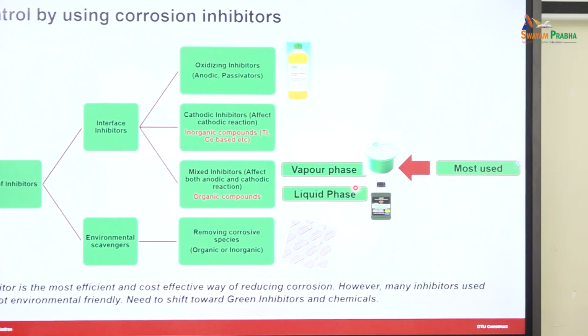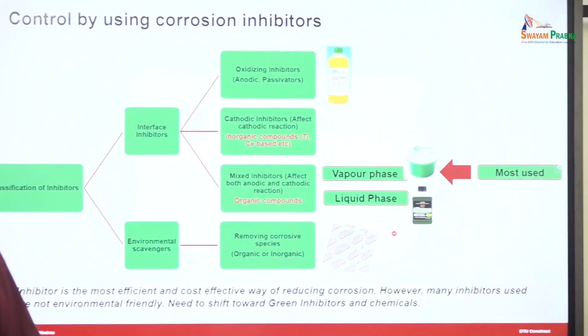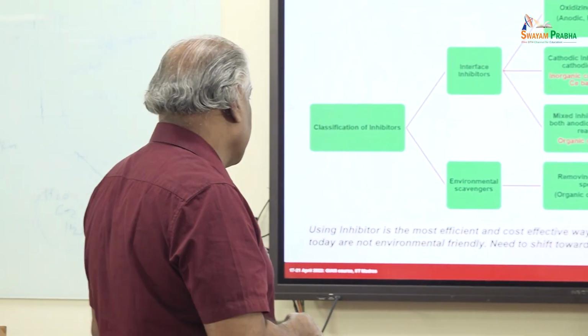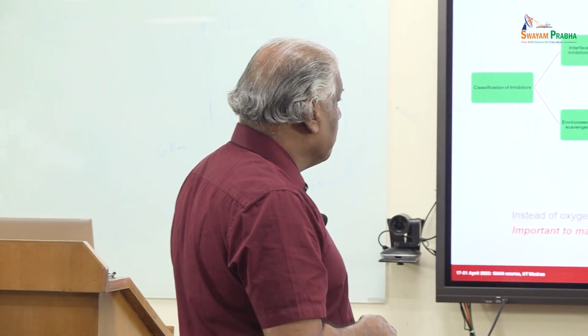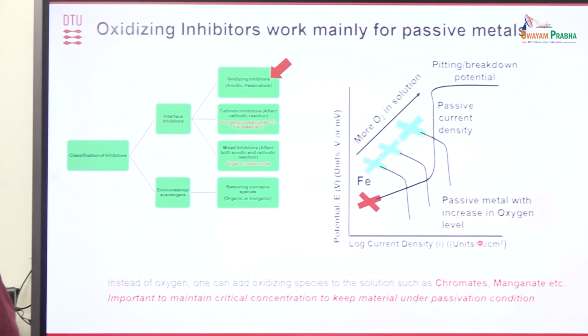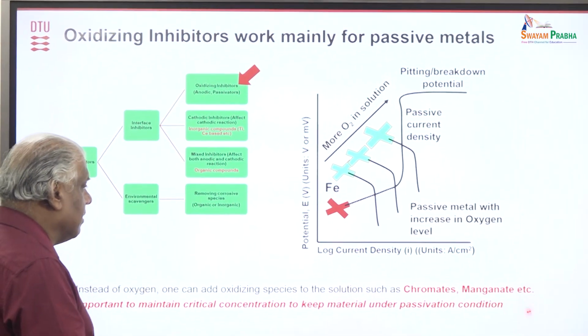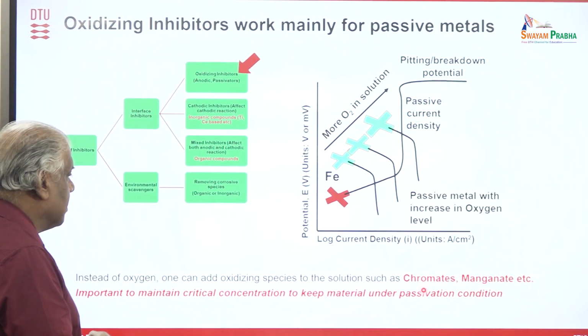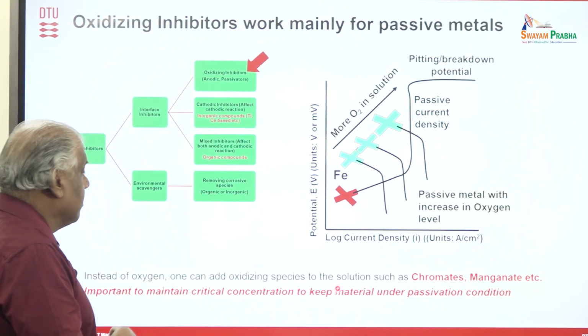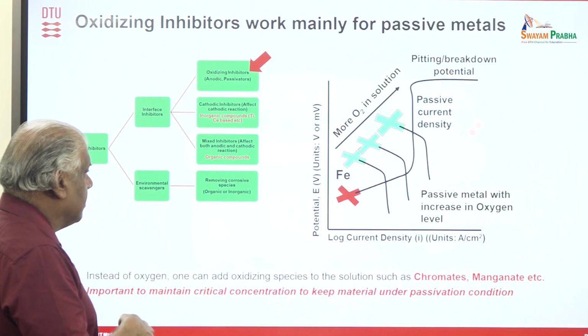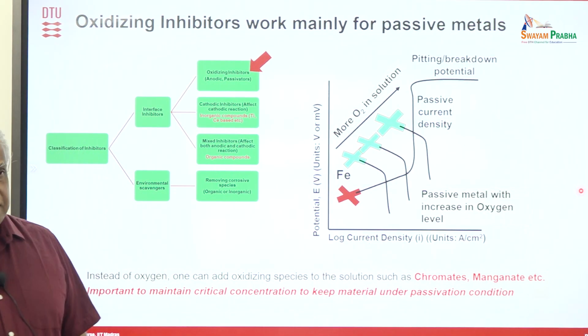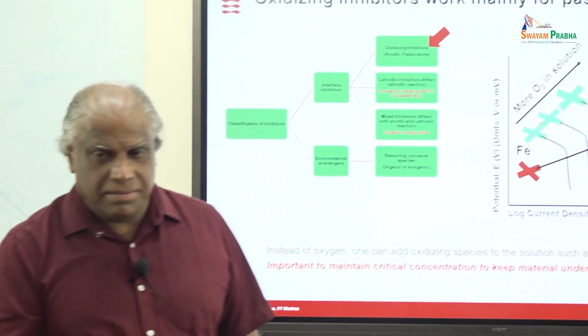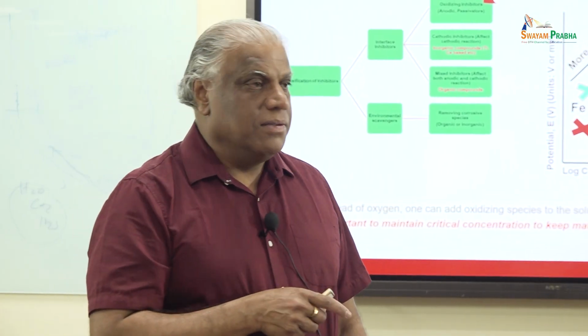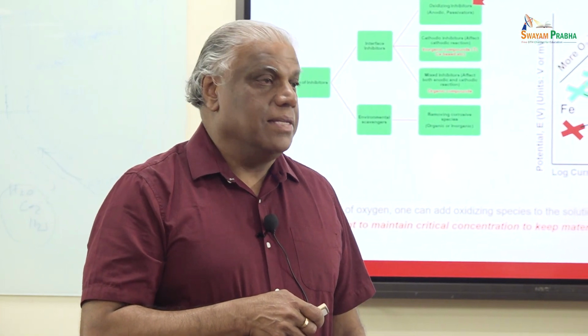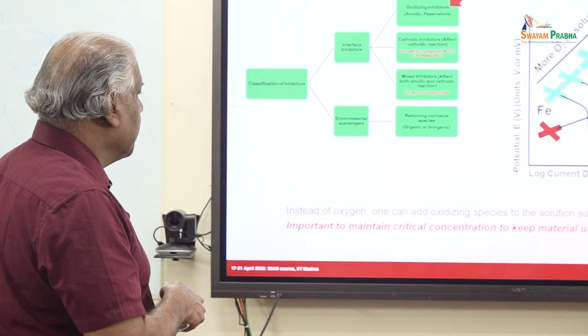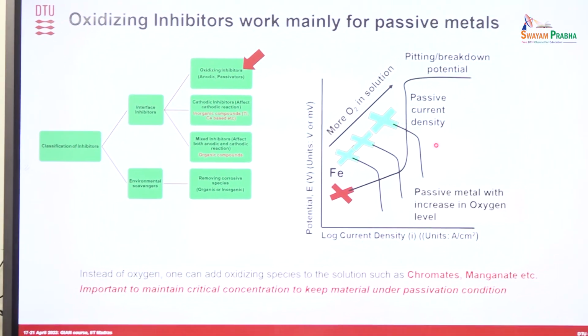And we discussed these environmental scavengers like hydrazine and sodium sulfite to remove the oxygen concentration. If you take oxidizing inhibitors, you can use chromates and manganate, and you can think about many other types of species that have enough oxidizing power. That means if you take a stainless steel material and want to use it for a heat exchanger, and you want to pass a coolant inside, you can add a little bit of chromate into the heat exchanger solution, and then you can raise the potential into the passive region, and that way it is protected inside.